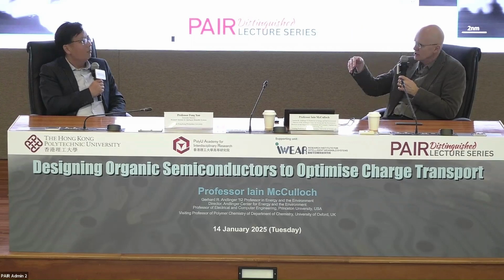So alkylation close to the backbone is good, because then you can get ion penetration to a certain extent, but without disruption of the backbone. So even if it swells a little bit, it doesn't seem to have the same consequential effect.